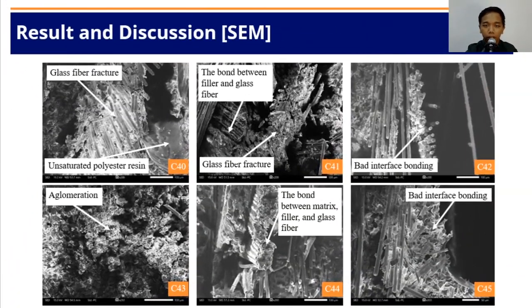Okay, let's move on to the result of SEM observation. As we can see, the following images are the result of GFRP composite scanning electron microscope observation that have gone through impact testing. From the result of the SEM observation, the sample without a filler, or C40 composite, shows a fairly good interfacial bond between the fiber and the unsaturated polyester resin.